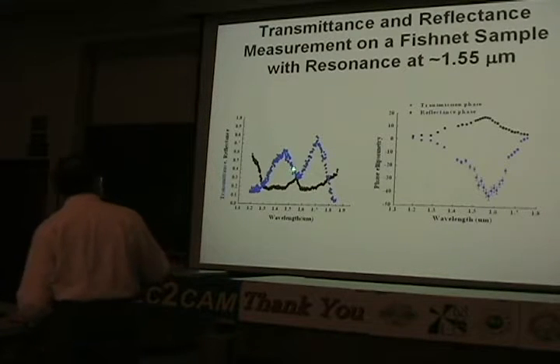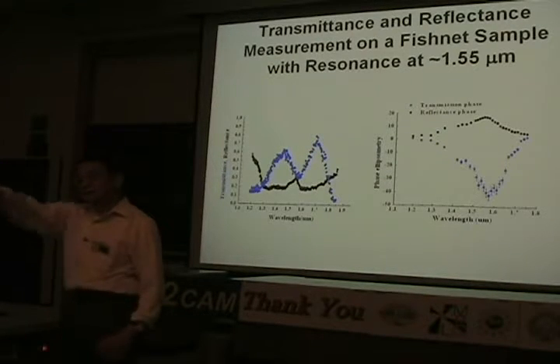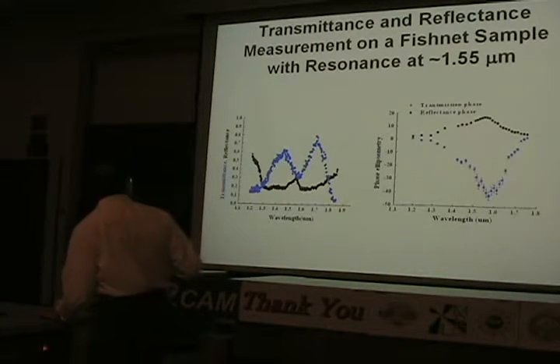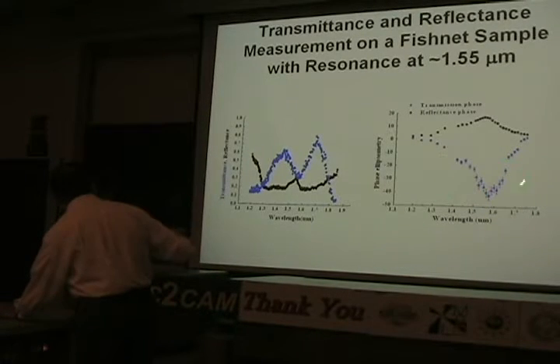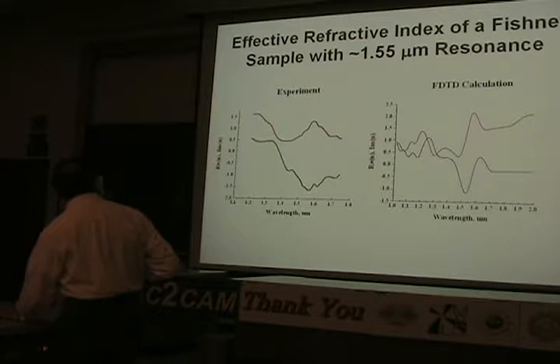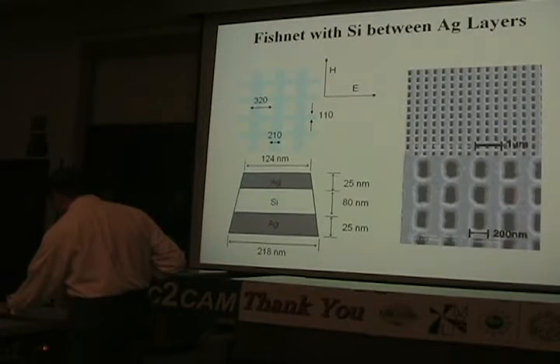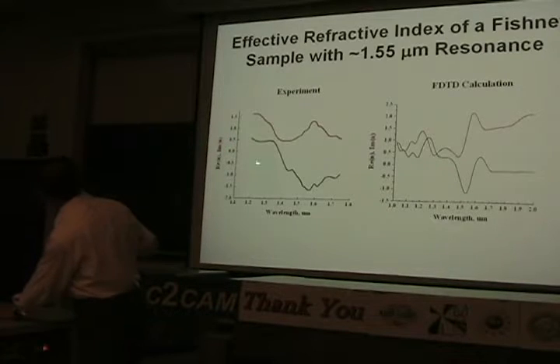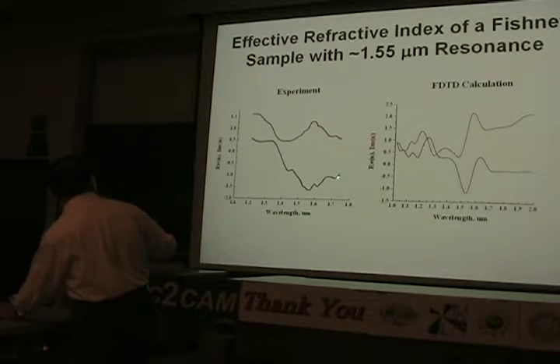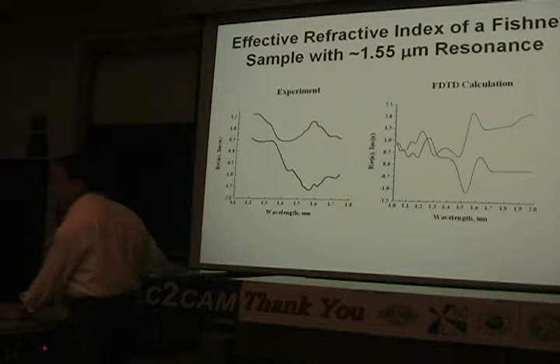And then we did the measurements, and indeed again, here you see only epsilon less than 0 in this region, and in this region epsilon less than 0 and mu less than 0. So the transmission rises again. And here are the phase measurements correspondingly. But again, we can use real N and imaginary N, and you can see again for refractive index N, 0 is here, so in this whole region around 1.5 micron is all negative.